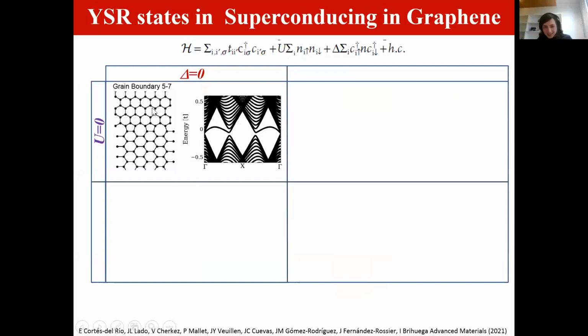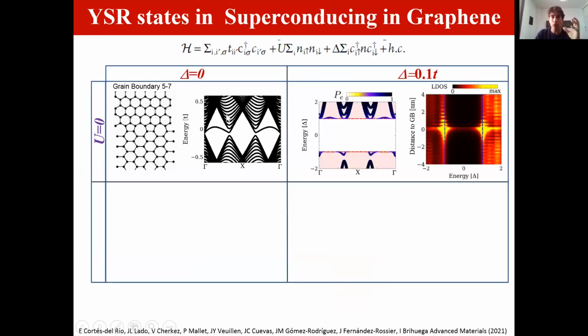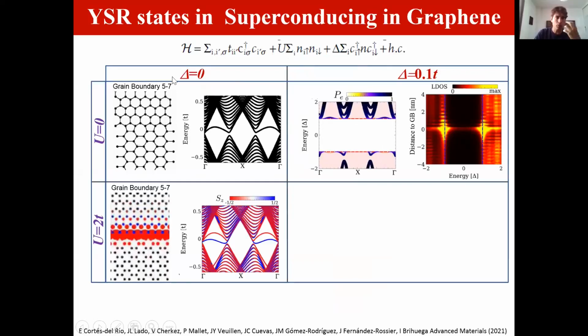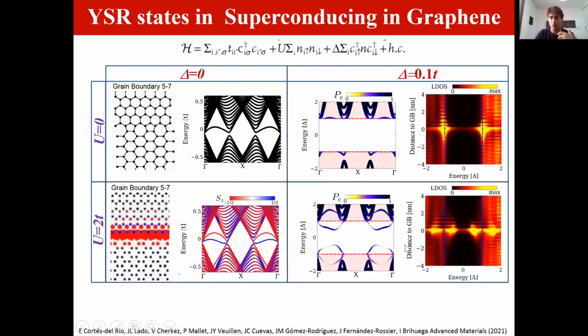So this is this flat state, which is this localized state on the grain boundary. When we now introduce superconductivity, we see the opening of a gap. Still, the localized state is outside the gap. There are no in-gap states. So now we introduce interactions with no gap. Okay, there is no superconductivity, but we introduce interactions, and we see the spin splitting of this band. And when we introduce both interactions and superconductivity, we see the in-gap state. We see the development of these Yu-Shiba-Rusinov in-gap states, the same as we were seeing in the experiment.